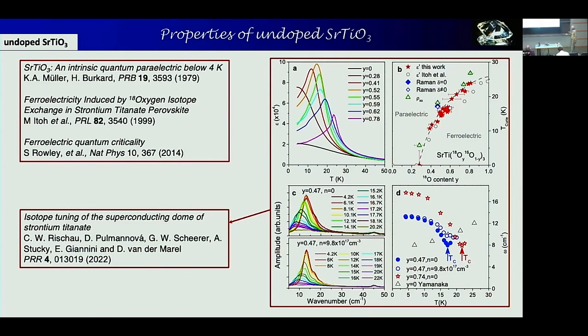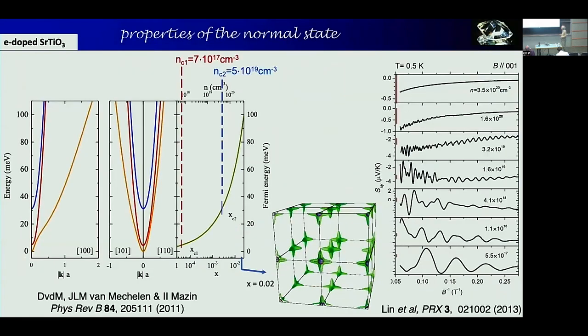So this you can tune, and this is a diagram, temperature versus oxygen 18 content, where you see that for precisely oxygen 16 here, the temperature goes to 0 Kelvin there, it's just paraelectric all the way. And now you put in oxygen 18, at some point you hit this quantum transition, and now it starts to become ferroelectric over here. And so at close to 100% doping, you have to go to 25 Kelvin, and that's your Curie temperature in the oxygen 18 strontium titanate. There's a lot more to say about it, but I'll not go into all these details.